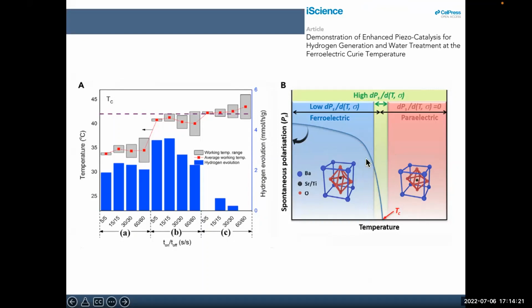In this region here, very close to the Curie temperature, you'd expect much higher piezoelectric activity, because it's very easy then to change the polarization with stress, and you also get much higher permittivities. A whole range of properties are maximized at this condition.